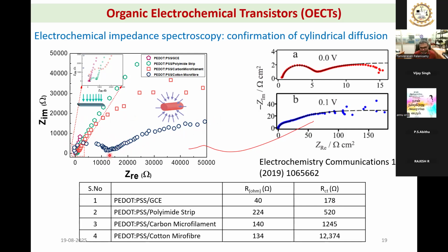For a cylindrical diffusion, it will show a less sloping behavior. You can see here, this is from the literature. So we have also observed for our PEDOT:PSS coated on cotton microfiber, we also got a similar profile. So with the impedance spectroscopy, we confirmed that our electrode has a good cylindrical diffusion. And to confirm it, we have also tested some other electrodes.